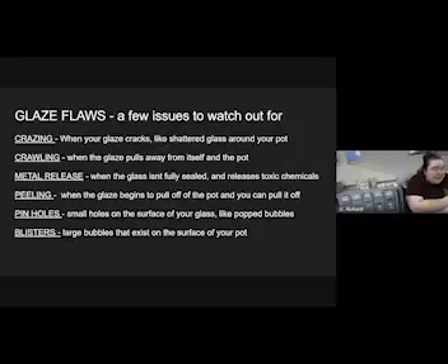Crawling is when the glaze pulls away from itself and the pot. Crawling happens sometimes when you leave a big spot of moisture while you're glazing and there was no room for that glaze to adhere to your bisque piece. And when we get into glazing, we'll go back over this, so don't stress if we don't get it down perfectly now. Metal release. Now this is the one we really want to work for,